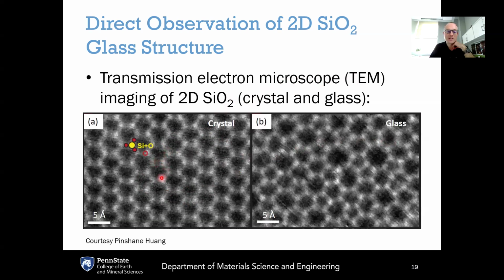You can see here, these are the six-membered rings that are forming. This is in the crystal state. There are six-membered rings of silica, and you can see how these rings come together to form this perfectly ordered structure in the crystal. In the glassy state, oh, by the way, the silica are tetrahedra, so this is actually bilayers of the crystal and the glass. There's actually two atomic layers. The two atomic layers are identical. The fourth bond is out of the plane here. And so you can imagine two identical layers on top of each other. That's what we're looking at here in both the crystal and in the glassy state. And so the coordination number of the silica appears to be 3 here because the fourth bond is coming out of the plane.